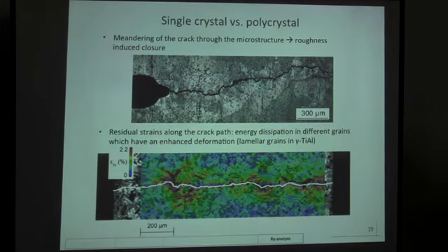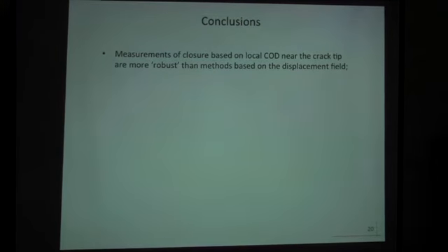So that's the end of my talk. The conclusion that we have taken in this activity is that for estimating closure levels, the COD measurements are much more reliable. Unfortunately, you have to take them close enough to the crack tip.